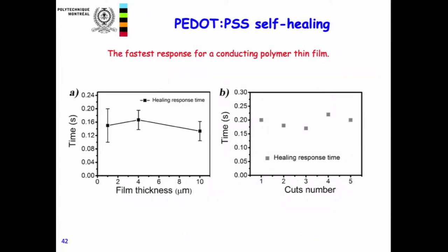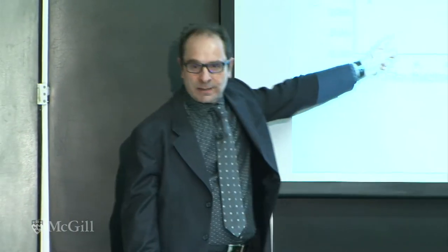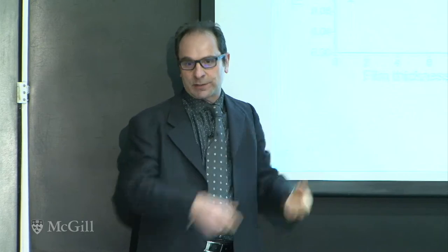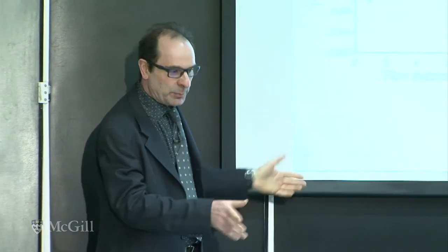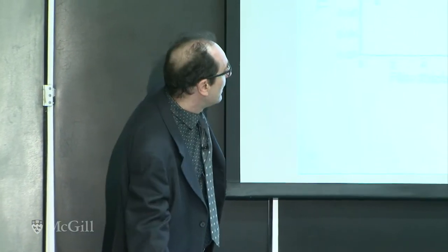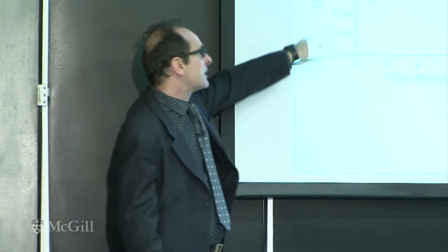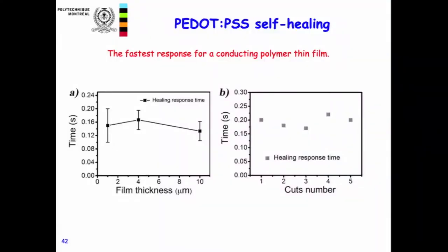Sorry? Yes. Are you applying a field when you're healing? No. We did with a field, but you don't need the field. In the case I showed you, yes, because we were powering the LED, but we can stop applying the field and it always works. What we have here also very interesting is the response time, which does not depend on the number of cuts. So it stays always around 0.2 seconds, so 200 milliseconds. But this is more related to the resolution limit of our instrument.